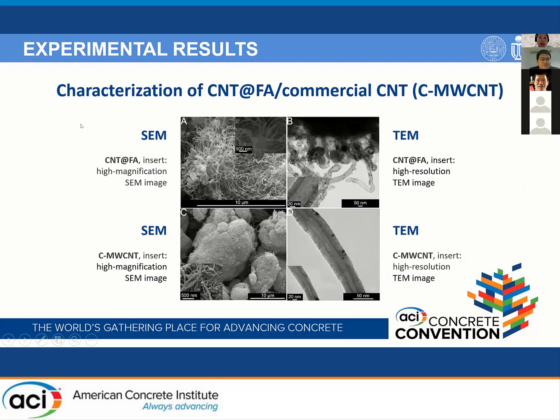After the synthesis process, we used SEM and TEM techniques to characterize the CNT and FA particles, and the commercial carbon nanotubes were also characterized for comparison. And the result is shown in this figure. Figure A and Figure B are the SEM and TEM images of synthesized CNT and FA particles. And Figure C and Figure D show the morphology of commercial carbon nanotubes. From Figure A and Figure B, we can see that carbon nanotubes have been successfully synthesized on the surface of fly ash particles. And compared with commercial carbon nanotubes, synthesized carbon nanotubes seem to be more fluffy.